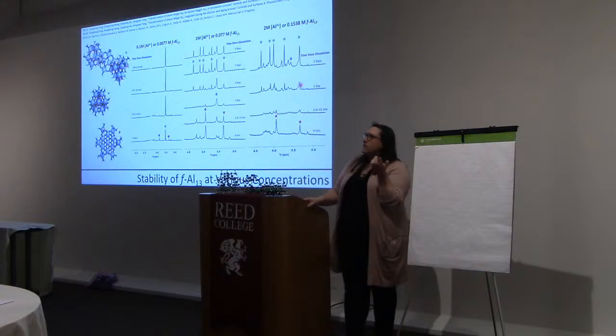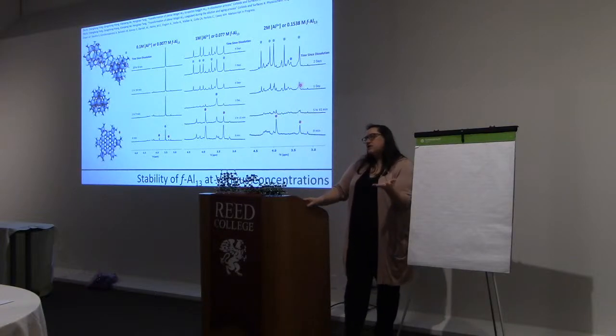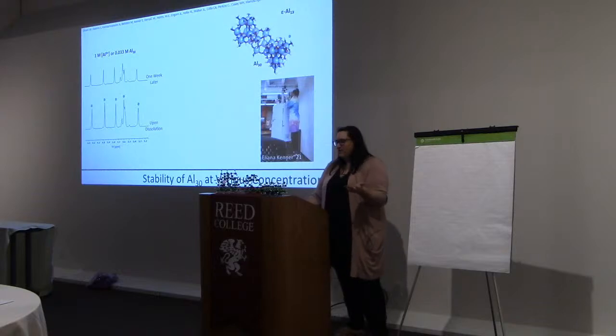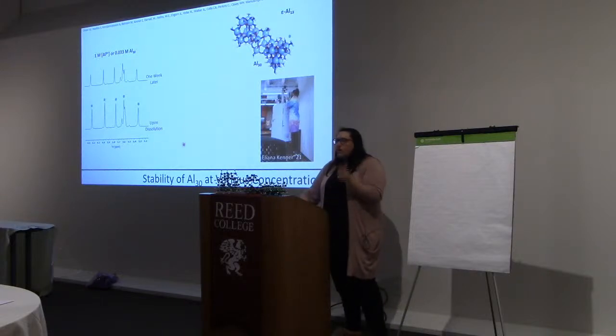So the next thing we decided to look at was, okay, well, 30 is forming in these solutions. We know that the Keggin is pretty stable unless you heat it. So let's just look at our 30, our cluster over time, and see what it does. And so here at 1 molar, we dissolved our 30-mer, and 1 week later, it looked pretty much the same. There's a little bit of impurity in there, but the signals didn't change after a week. We looked at it again. Oh, there's a little bit of epsilon I decided to label for you.